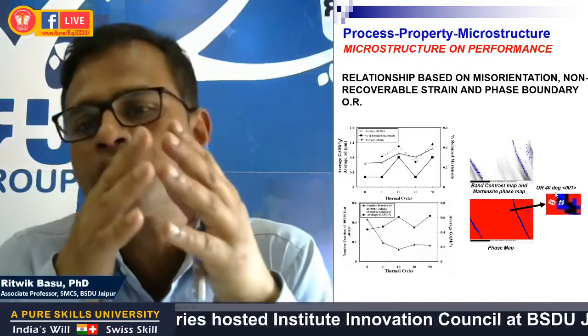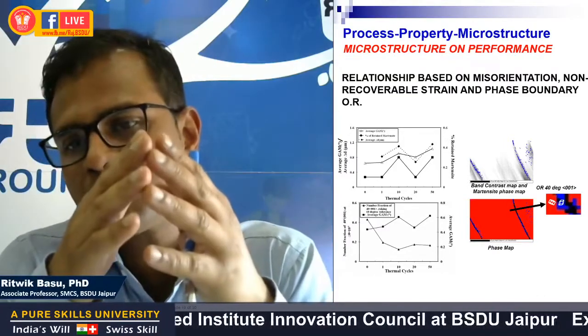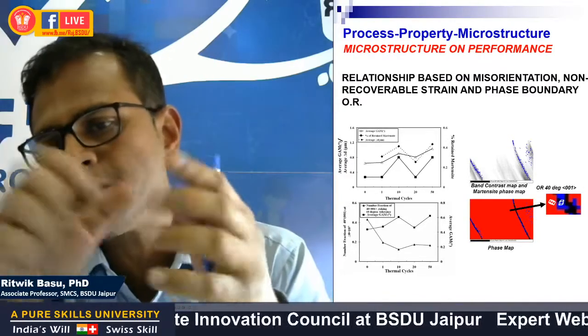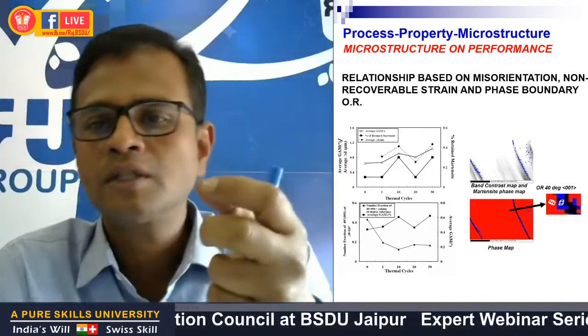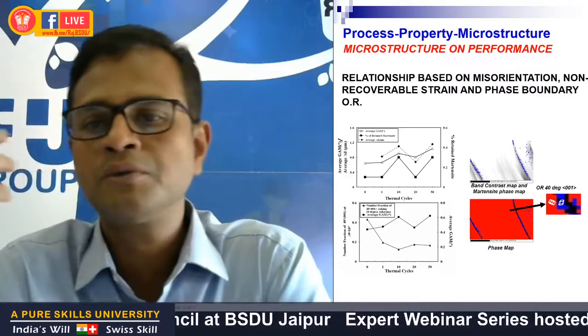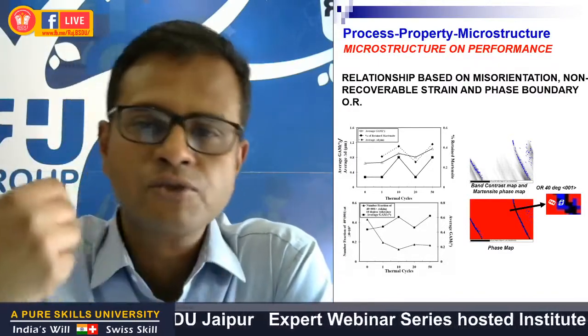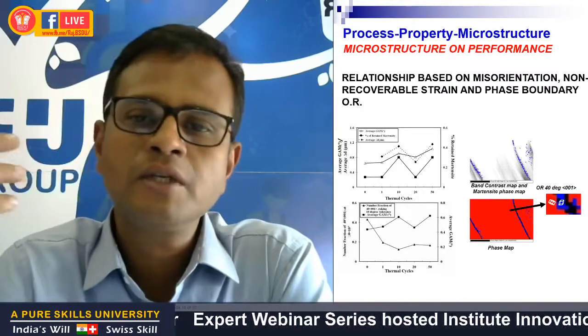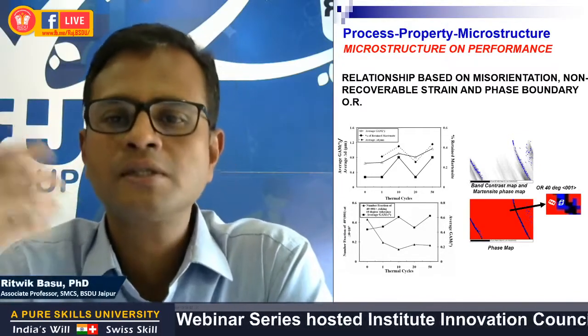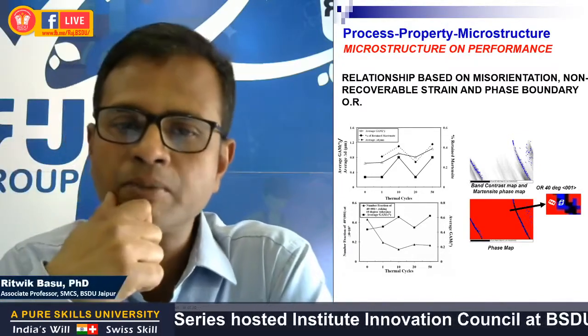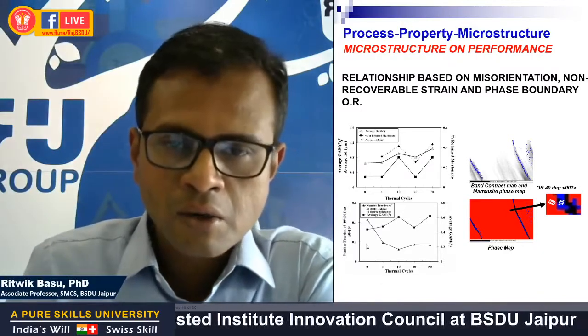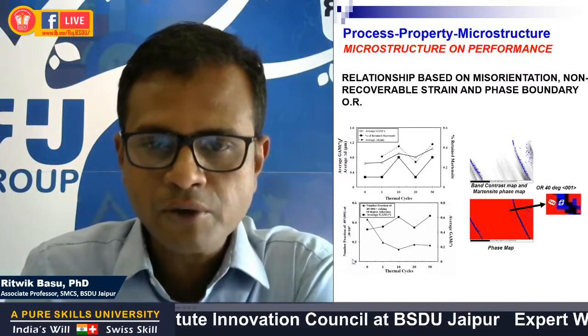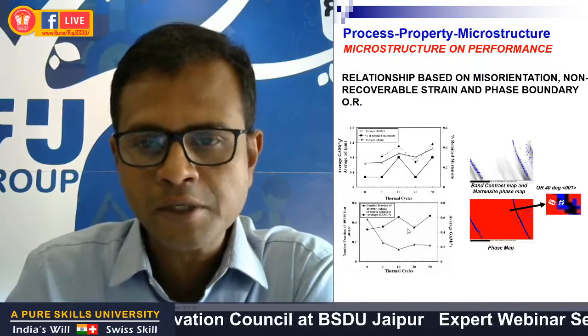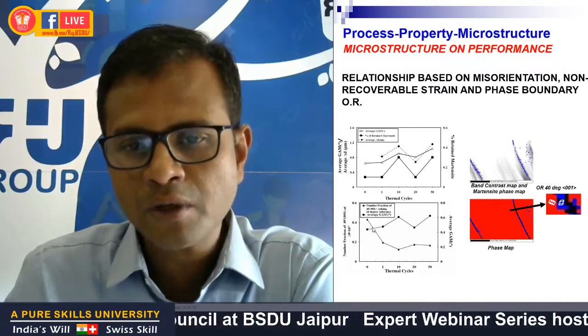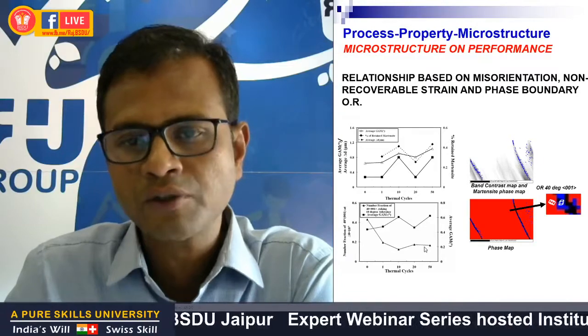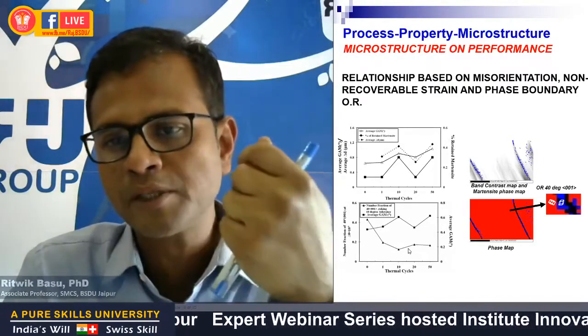So any deviation from the ideal orientation relationship or phase boundary relationship of 40 degrees <001> will not allow the martensite to retain or to revert back to austenite during the reverse transformation, and that will eventually lead to a higher fraction of martensite during successive thermal cycles. So we found that with an increased number of thermal cycles, the average misorientation increased, and that led to a corresponding drop in the number fraction of the 40 degree <001> phase boundaries.